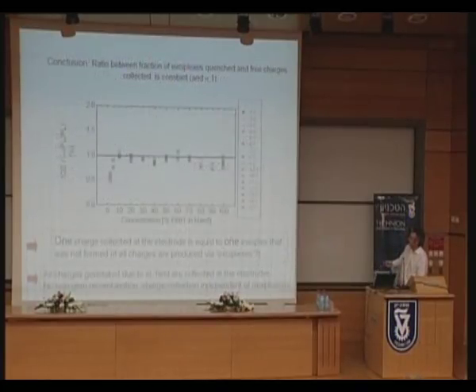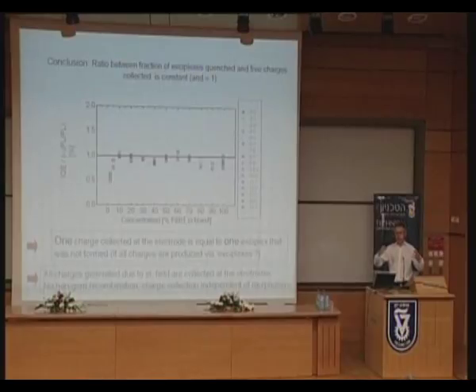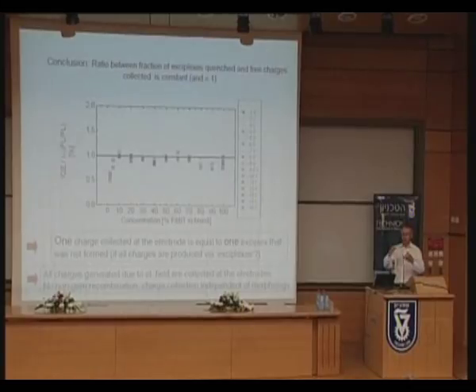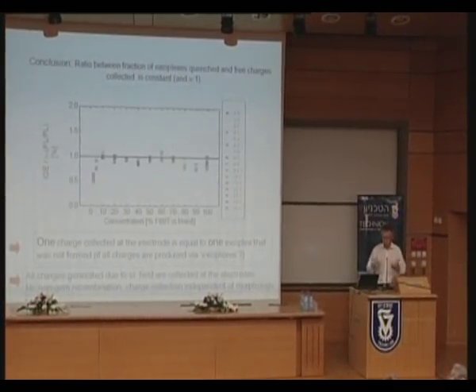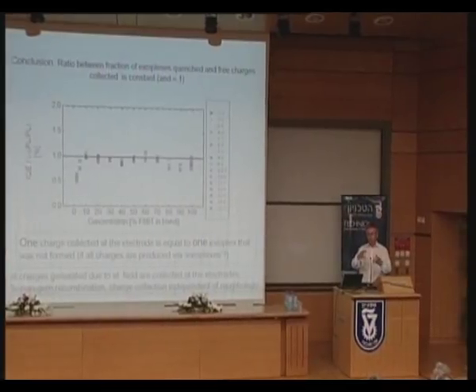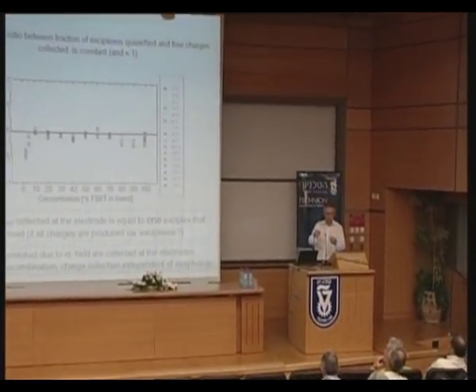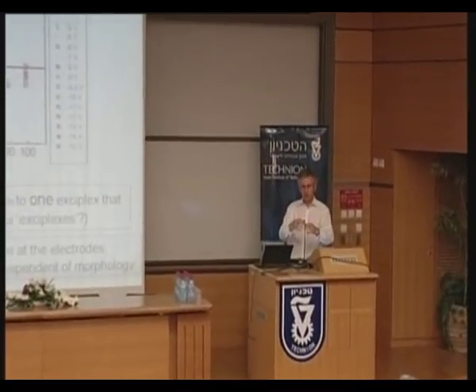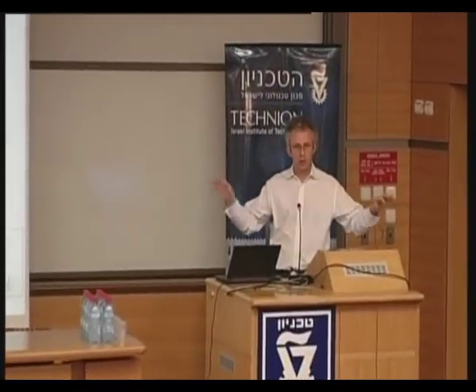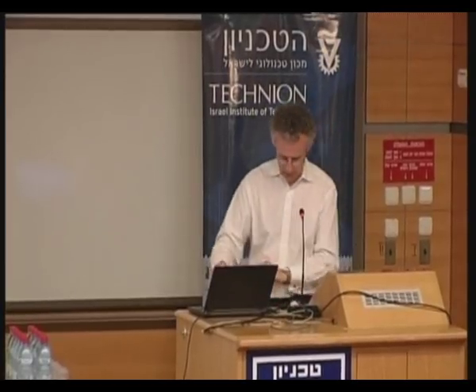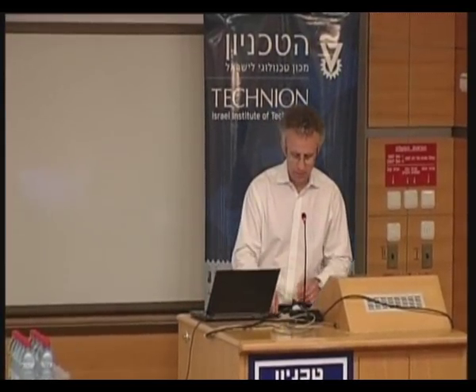And one has to put a few caveats into the argument, but we have this ratio of one, and what that is showing is that if we don't do anything, if we don't have any external bias or internal bias set up by the open circuit voltage, we end up with charges that are initially separated but then get stuck, and we need an external field to pull them apart. We can see this one-to-one correspondence between either luminescence or charge in the external circuit. And that does indicate a number of directions to go in to improve performance.